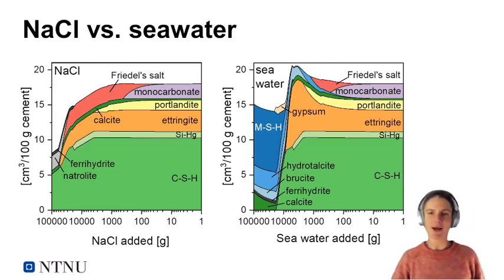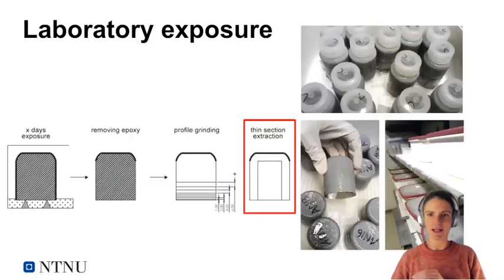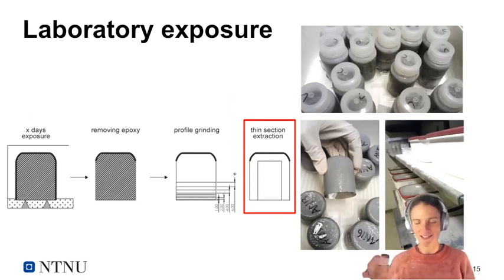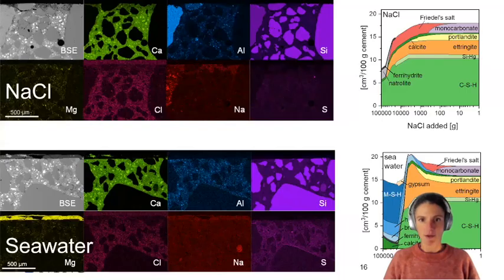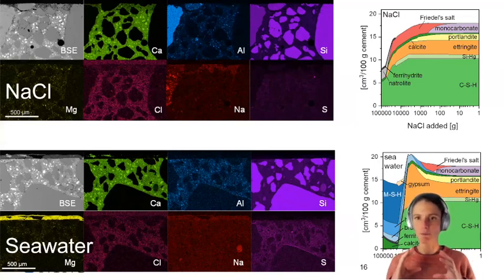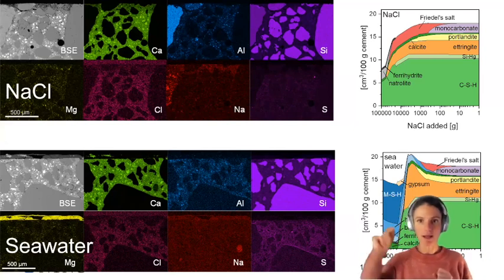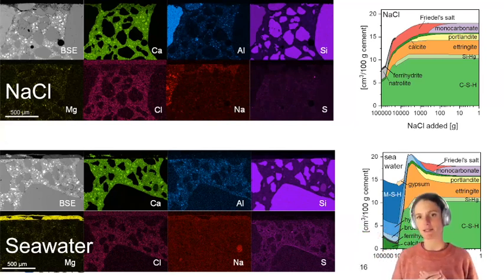So let's now see how these predictions match our experimental results. Again, I used a bunch of techniques to look at the hydrate assemblage, but I'll focus on the findings we got from looking at polished sections in the scanning electron microscope and looking at elemental maps. So here they are, elemental maps, which I took from a polished section of a sample exposed for 90 days to sodium chloride solution at the top, and at the bottom here, for 90 days to seawater. And this is for a Portland cement.